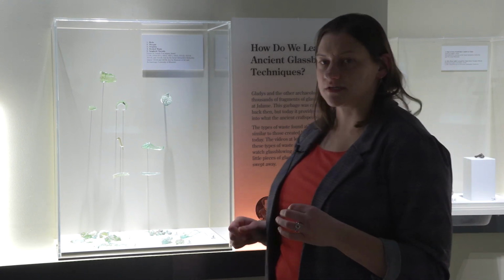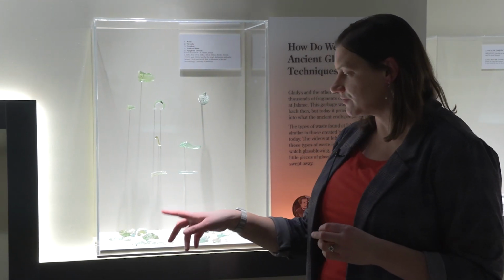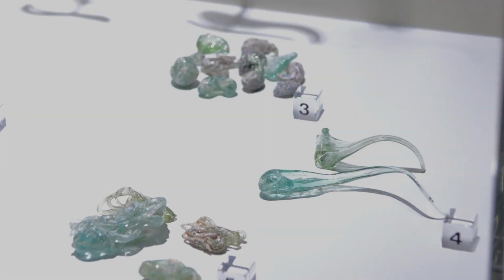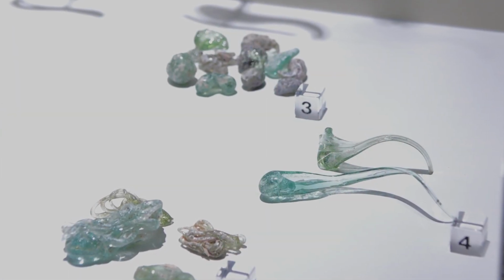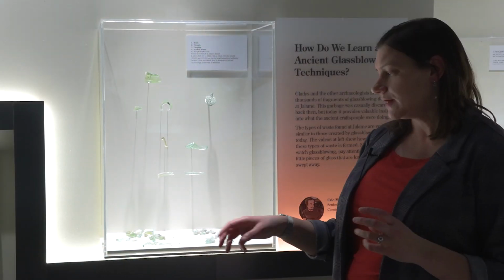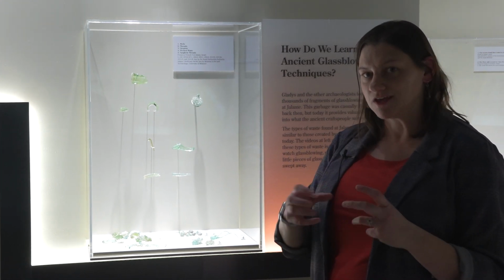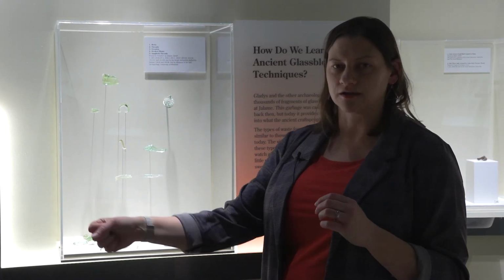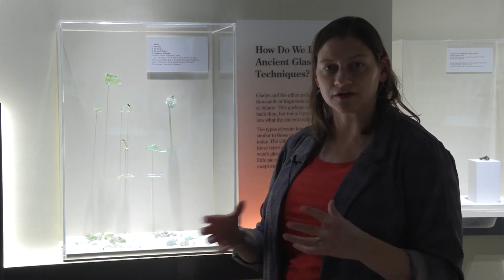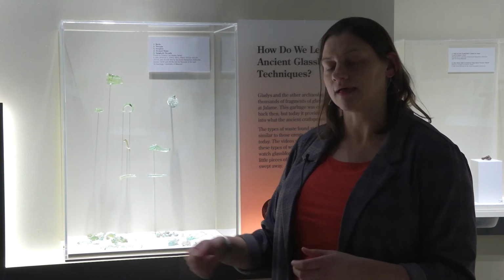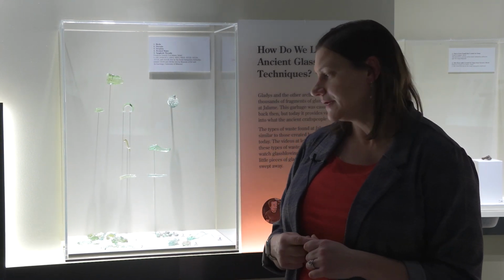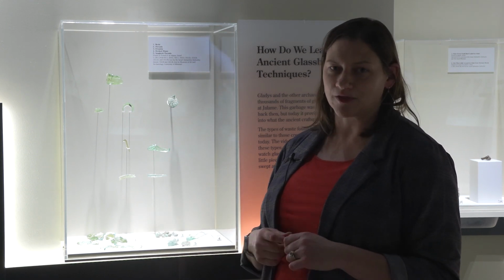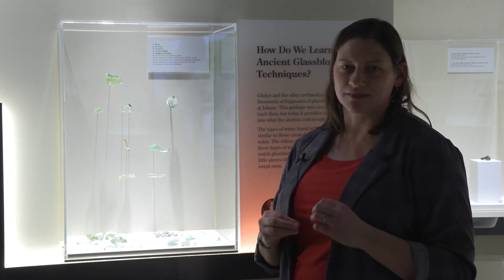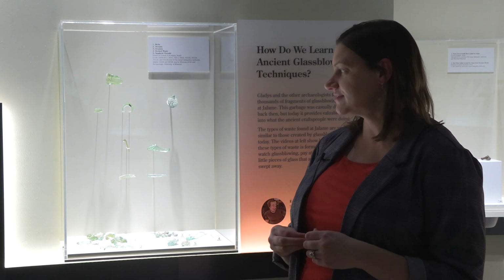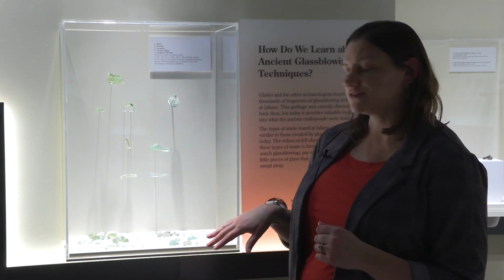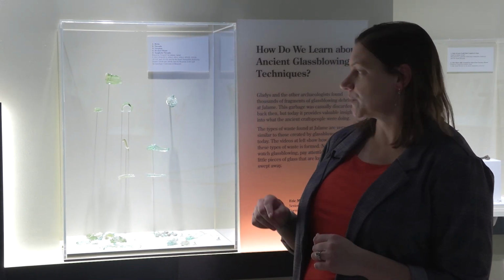Another really nice little detail from these moils is that some of them have this sort of cracking pattern on them. That's what happens to hot glass when it's submerged in water. It gets all these microfractures in it. So you'll still see glassblowers do this today. They'll take the end of their blowpipe and they'll just dump it in a bucket of water to help cool down the glass more quickly and allow them to break that moil off the end of the blowpipe. The exact same thing they were doing at Jalame. So it's a really nice connection between ancient and modern manufacturing methods. All these other pieces are other further remnants of the glassblowing process.